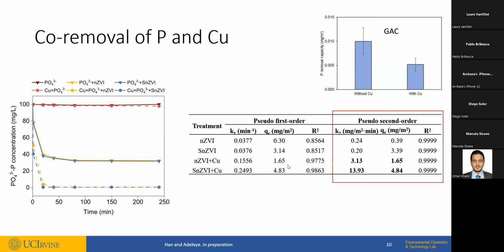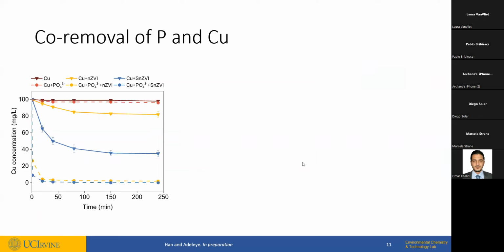So what about copper? We had to measure the two independently, but the story is actually quite similar. When there is no treatment, there is no removal over 4 hours. When we use NZVI, we see about 20% removal. When we use SNZVI, we see about 60% removal after 4 hours. When we add phosphate and we measure copper removal, we remove the whole copper within about an hour, whether we use NZVI or SNZVI. So the result is pretty consistent.